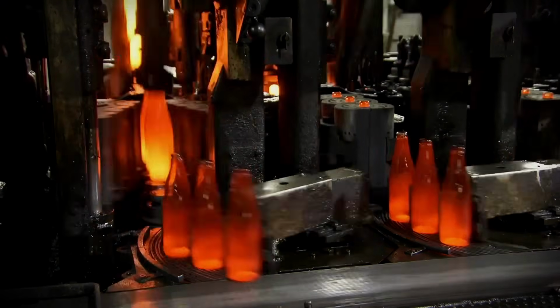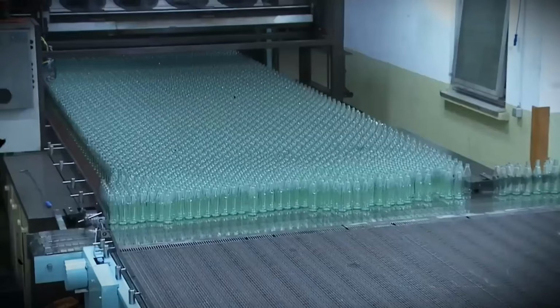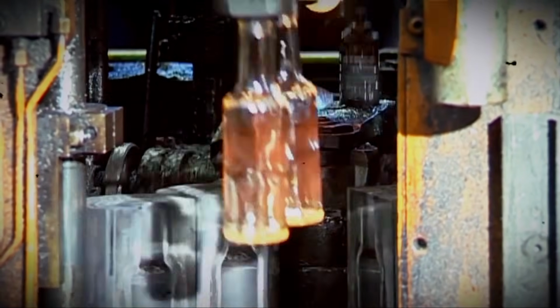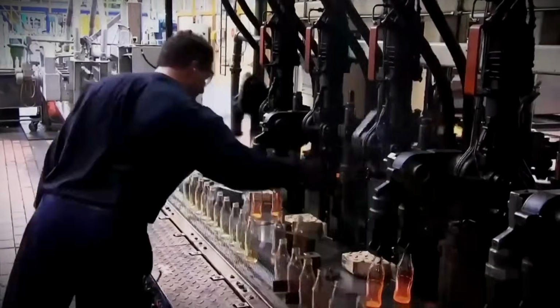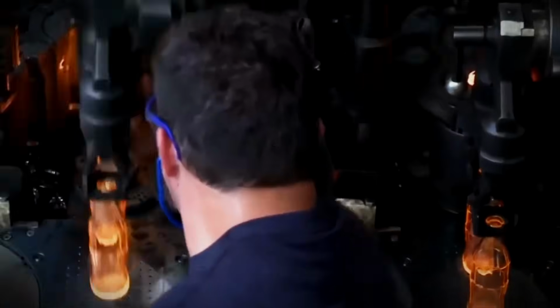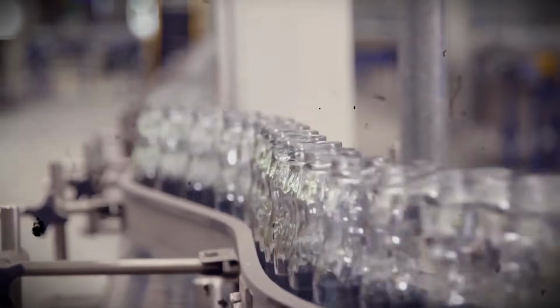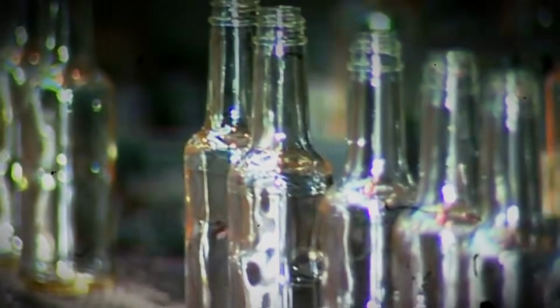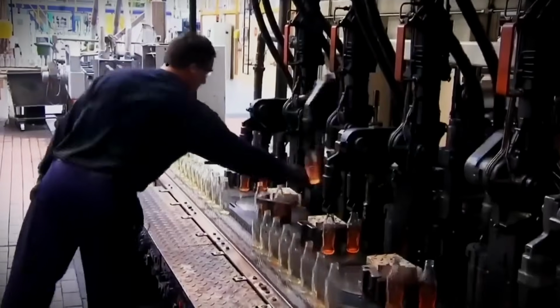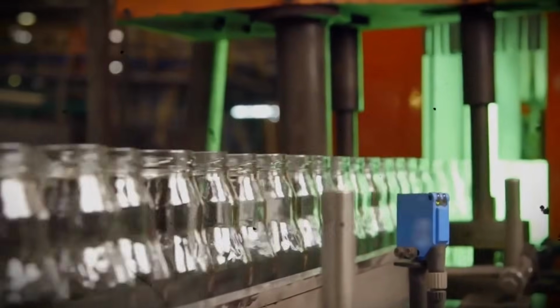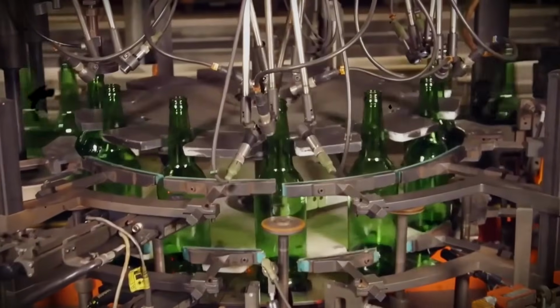Fresh bottles travel through an annealing lehr for 30 to 45 minutes, cooling gradually. Then every single bottle faces automated inspection. High-speed cameras check for cracks and defects. Infrared sensors detect stress patterns. Bottles must withstand at least 90 pounds per square inch internal pressure. Any failures get crushed and recycled back to the batch house.